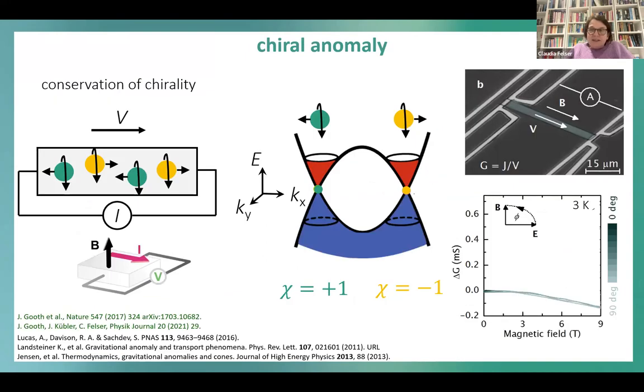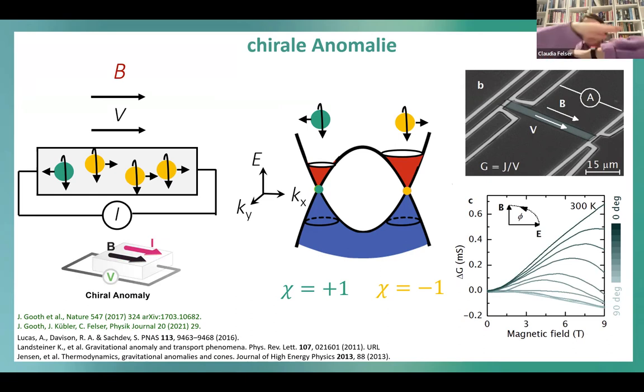You see here on the right side simply a sketch. What we did there, we measured the electric field and the magnetic field in the same direction. The first direction is like in a Hall measurement, where they are perpendicular to each other, and you see the conductivity here. Then you switch, on the next slide, the direction of the magnetic field into the direction of the electric current, and you see a giant change in the conductivity, and this was exactly what was predicted. And you see at the same time that in the sketch you have more yellow electrons now than green electrons.